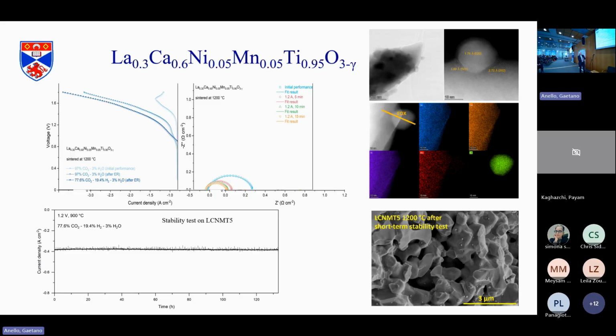And stability is long-term, as stable as you can get without your colleagues switching off the gas line, basically. So Nishi was not pleased when the gas line was switched off on this experiment. Again, you're running in pure CO2, so you don't pre-reduce the electrode. You reduce it electrochemically, and you don't have to protect it. And from the SEM, again, you see it's stable.